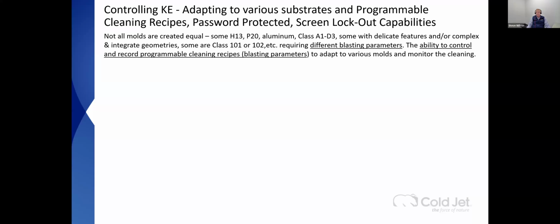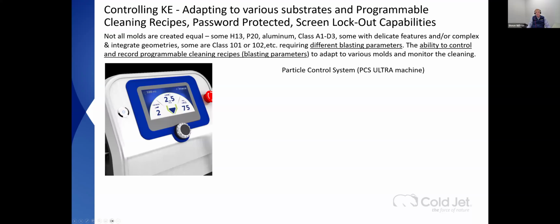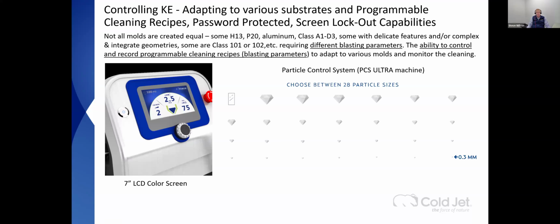We can clean that without damaging. That's how delicate you can be. Or some complex geometries on a mold. Is my mold a 101, where I'm expecting it to last 1,000,000 cycles? Is it a 105, just a prototype tool? I just need the ability to adapt and to adjust. We have systems on the PCS Ultra where you do that. You have the ability to choose between 28 particle sizes, from 3 millimeter all the way down to 0.3, so you can control the amount of kinetic energy that goes into the process.